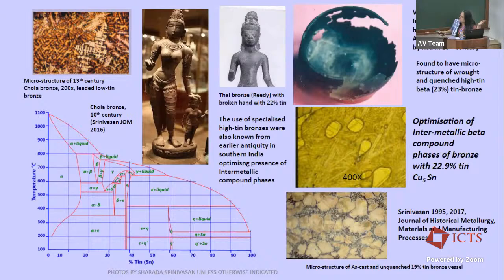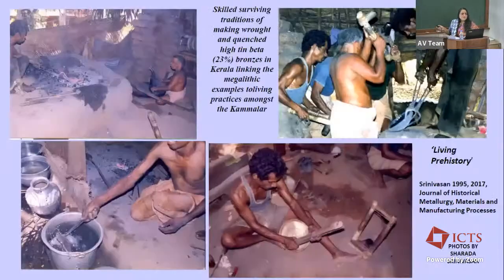Because if you rapidly cool from this temperature down to room temperature, you can see that that beta phase is retained. Otherwise, it won't be retained and you get all these other phases. And that's what happens here. So you can look at the structure and tell how it was made, that this is a hot-worked quenched beta bronze. And it's amazing that this was already in vogue in the South Indian Iron Age.